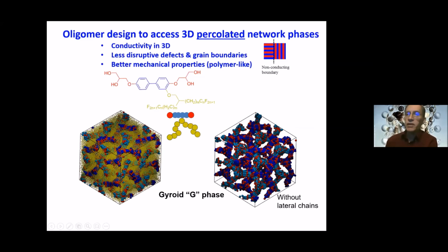In this picture over here, I'm showing things without lateral chains, just to make it simple. From now on, you will not really see the lateral chains. But you see that these struts have 2 different shades of blue to underline the fact that there are really 2 networks that are sort of interweaving each other, but they never touch and go sort of forever in 3 dimensions. So a structure like this will be ideal, but it turns out that this chemistry is not best for this dual conductivity we're after. So clearly we'll have to change the chemistry.